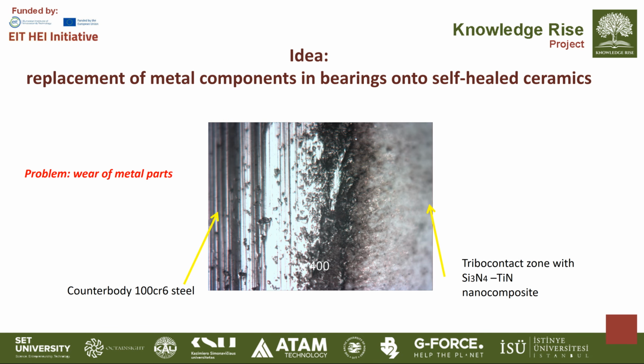In conventional bearings, metal components such as steel balls and races, commonly made from bearing steel, operate under high contact pressure and frictional loads. During prolonged use, these parts are exposed to mechanical wear, oxidation, and micro-welding, leading to surface damage, increased friction, and eventually failure. The image clearly shows a tribological contact between a bearing steel counterbody and a silicon nitride based nanocomposite surface, where steel experiences severe material transfer and abrasion. This degradation not only reduces bearing lifespan but also increases maintenance cost and limits performance for high temperature or corrosive environments.